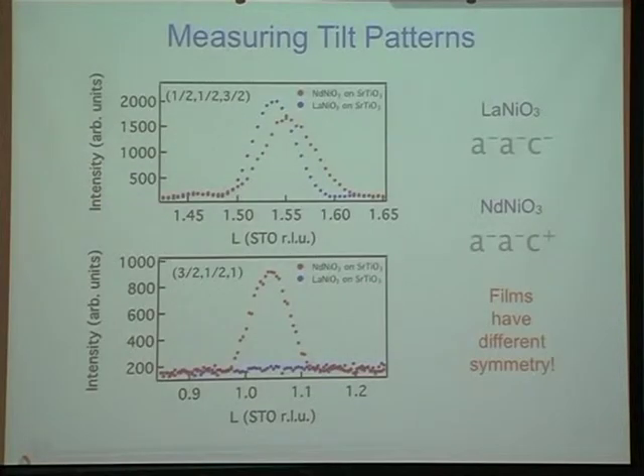And we actually measured this in the films, so we can go and measure the crystal structure in these films in the synchrotron, and we can show that the rotational patterns, even though you put these under very high tensile strain, still maintain a memory of the original rotational pattern. So rhombohedral still has this minus, minus, minus. The neodymium nickelate still has this minus, minus, plus. So you say, okay, well, why do I care? Why should I care about this?